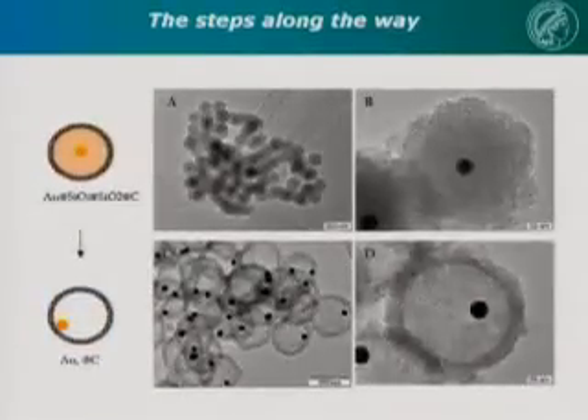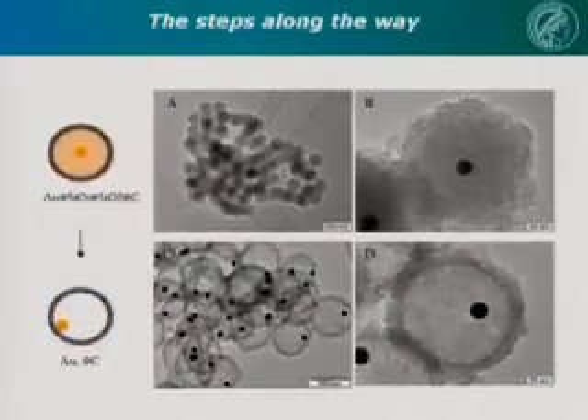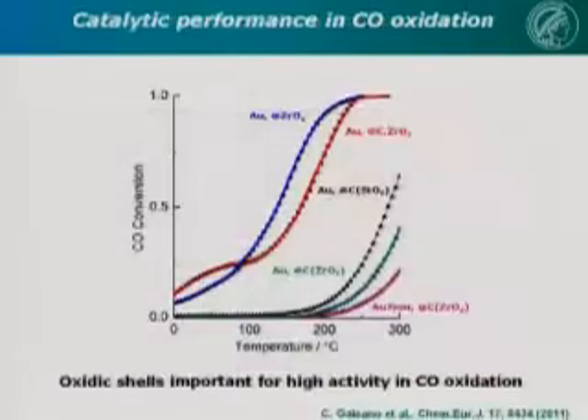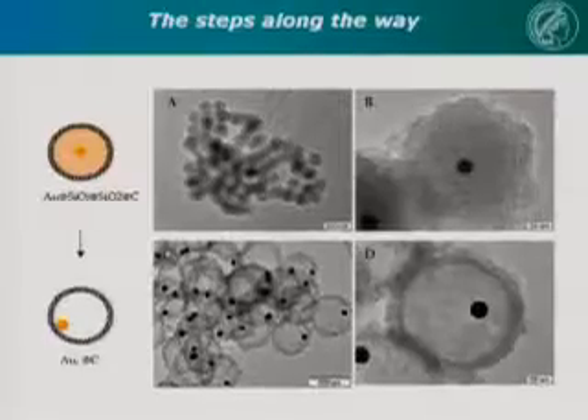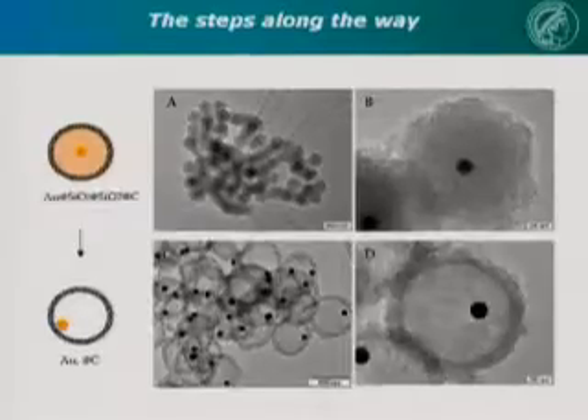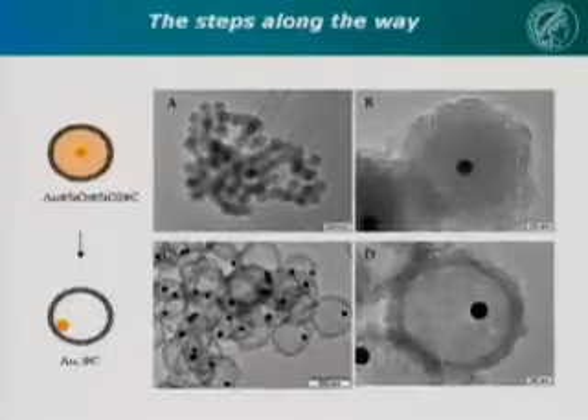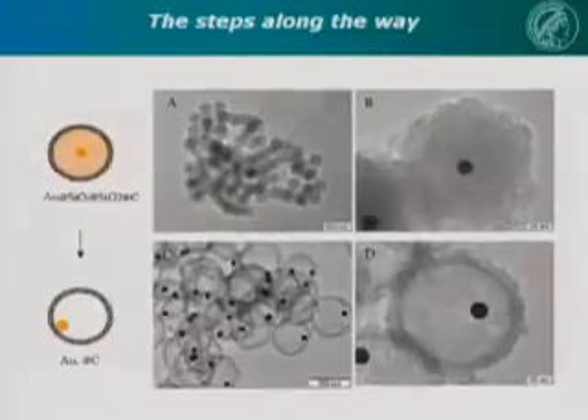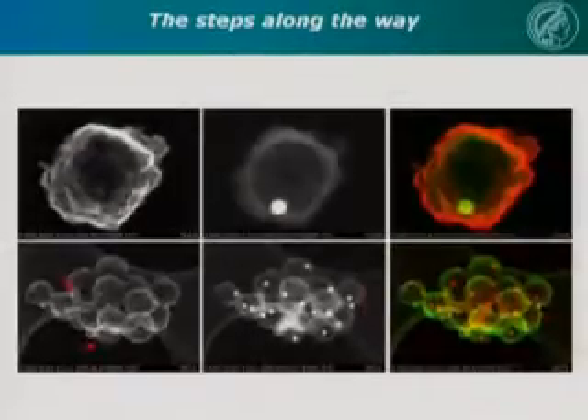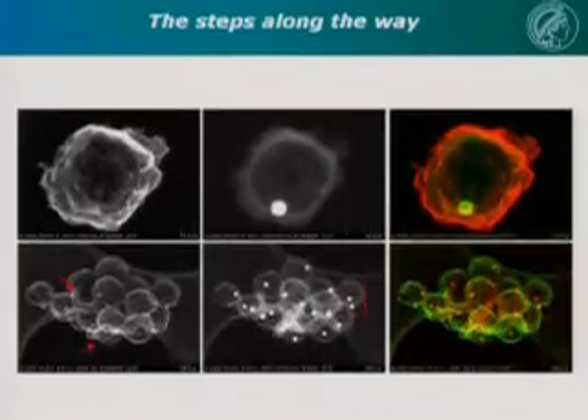Then we fill with the polymer here and carbonize, and it looks pretty much the same. And then we leach out the silica, and now we have the gold particles in a porous carbon shell. So we have replaced the zirconia or the silica by carbon, by this repeated templating process. This gives you basically the same information, but it looks a little bit nicer. So I like these color images.